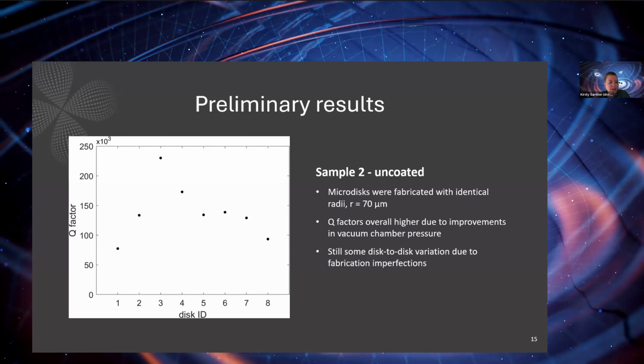We also measured slightly higher quality factors on this chip because we made some improvements to our vacuum chamber pressure, which is good. You can see there's still quite a bit of disk-to-disk variation in the quality factor because of fabrication imperfections. This isn't necessarily a problem. Going forward, now we know our disks are not going to be identical, and so we need to do measurements of a bare disk and then coat that disk and measure the same disk again. So we know what to do with this.